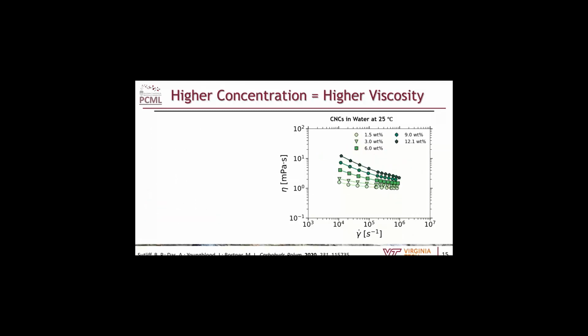Our next look was to see what happens when you change concentrations. As you might expect, when you increase your concentration, you have a much higher viscosity because you're adding more solid content to your material. When you decrease it, you're pretty much just testing water, so you're also going to get much more Newtonian flow because you no longer have these cellulose nanocrystals, these rigid rods that are able to bump into each other. You're basically just testing water with a little bit of dust in it.